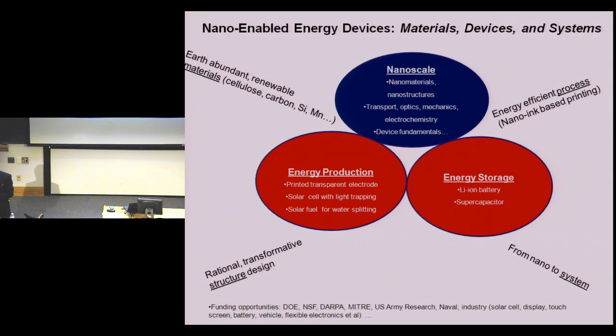And then the follow-up question is, in the devices you envision, what type of lifetime would cellulose have to have? And what are the factors that you think might be most constraining? I think there's no constraint for using cellulose as a battery material. Currently many major battery companies are replacing PVDF with cellulose as a binder. If they can use it as a binder for the battery electrode, that means electrochemically it should be stable, and in terms of cycling, it should also be stable.